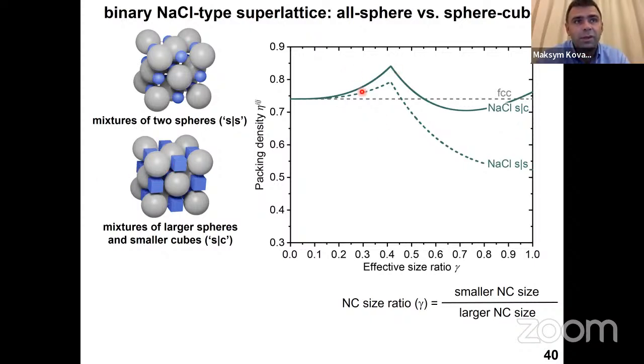And so here you see that, for instance, when you mix two spheres, they will have high packing density only in a specific size range. And only then you will have this lattice more stable than the phase separation into single component lattices. So basically you compete against phase separation, and you will win this competition only if your resulting lattice is denser or similarly dense. So with cubes, it's actually even easier because the cube of the same diameter as the sphere is larger. And so you can get actually higher packing densities when you switch from a sphere to a cube.